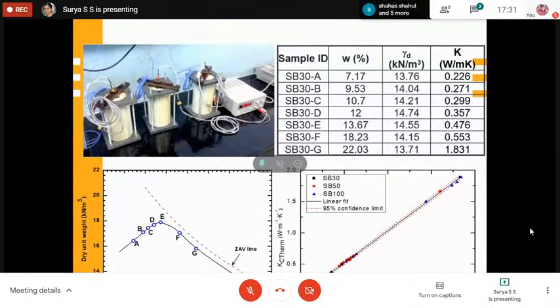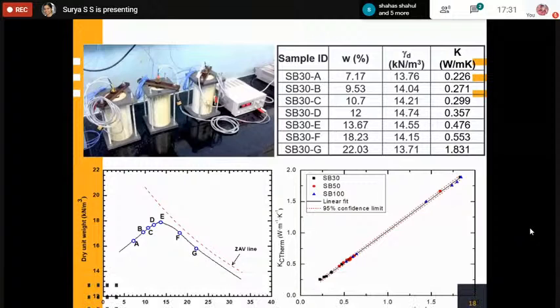CTherm is a commercial tool. They were compared, and we can see that both are matching together along the 45-degree line. So this was also revealing the accuracy of my probe. Similarly, different sand bentonite mixtures like SB10, SB30, SB50, SB70, SB100, etc. were tested for their thermal conductivity.